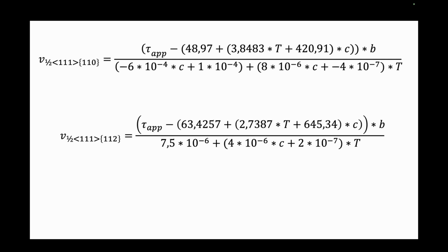And here, one can calculate the velocity of dislocation at different temperatures and different hydrogen concentrations. So you can do interpolation in between these values. Extrapolation might be difficult, so maybe you cannot go beyond these values like 0.5 hydrogen concentration, because you might see different dislocation activities at greater temperatures or hydrogen concentrations.